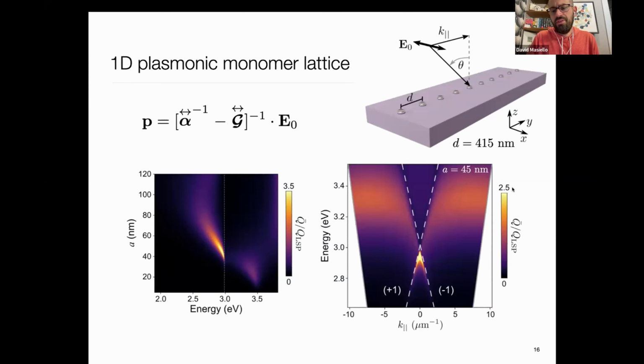And so what you see here is the momentum resolved absorption cross section as a function of tipping the angle of incidence of the excitation field for a lattice of 45 nanometer radius, 90 nanometer diameter particles separated by 415 nanometers. And so you see that strong energy momentum dispersion of the surface lattice resonance mode down here. This is the light-like hybridized mode. The matter-like hybridized mode is up here.